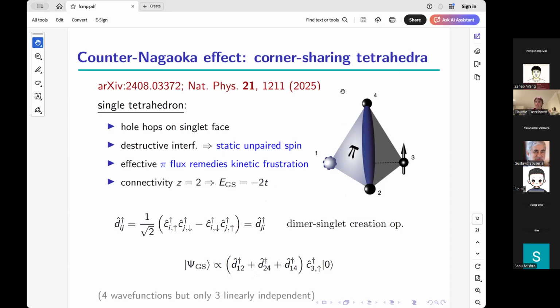And what has happened is that your hole hopping around a triangle would have killed itself by destructive interference because of the minus t hopping. However, the electrons 2 and 4 forming a singlet have effectively attached a pi flux to this plaquette, enabling the hole to hop around it resonantly. Right? So you have this flux attachment style physics of the two electron singlet allowing the hole to gain the kinetic energy, maximal kinetic energy that it can.